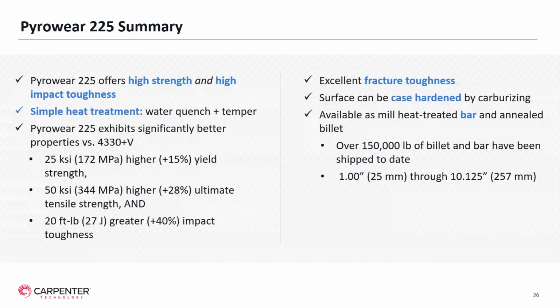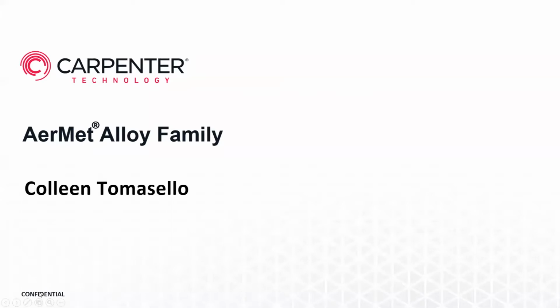The surface can be case hardened by carburizing, and the material is available as mill heat treated bar in the quenched and tempered condition or annealed billet. We've shipped over 150,000 pounds of bar and billet to date in sizes ranging from 1 inch to 10 1/8 inch diameter. Thank you all very much for your attention. I'll be happy to answer any questions if anybody has any. If not, I'll hand it back over to Colleen.